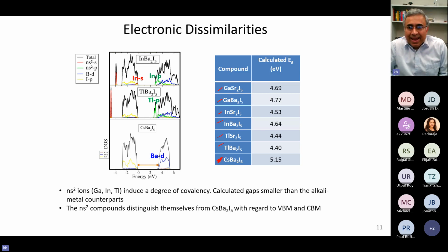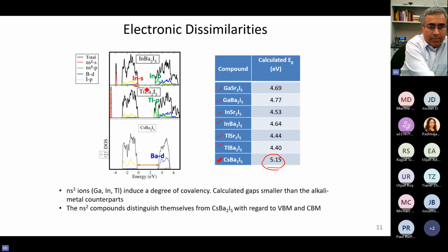And if you look at their band gaps, the band gaps are slightly less, not a whole lot, but still some difference, slightly lesser than cesium barium iodide. Cesium barium iodide has the highest band gap here, and a smaller band gap is also beneficial in terms of how many electron hole pairs you can create, and therefore how many of them recombine and give you light. So smaller band gap is not a bad characteristic. But obviously we are missing cesium now. We have these Ns2 atoms, and therefore the electronic structure looks different. For example, in case of indium barium iodide, you have indium S states right there near the bottom of the valence band, and near the top of the conduction band, you have indium P states.